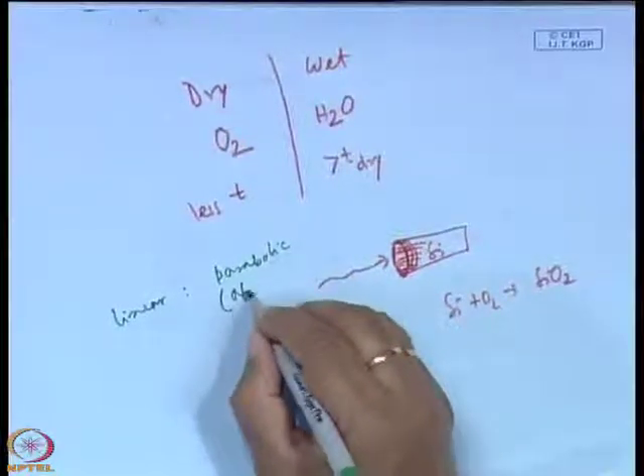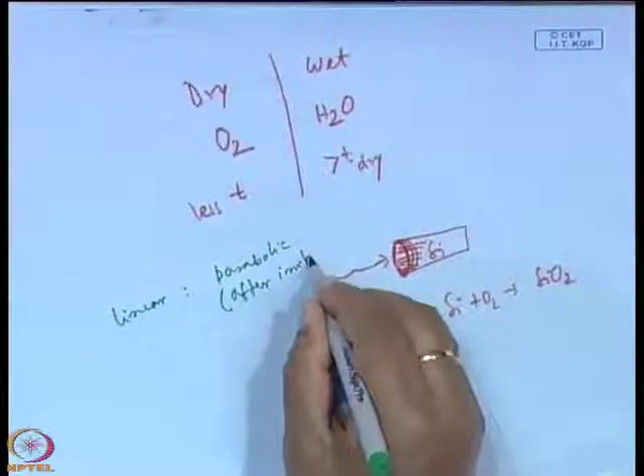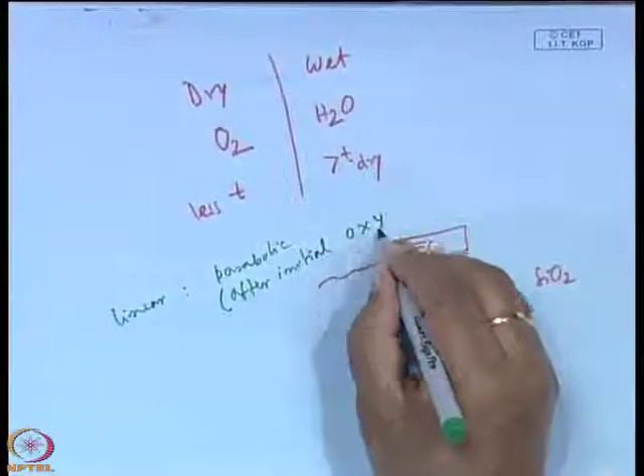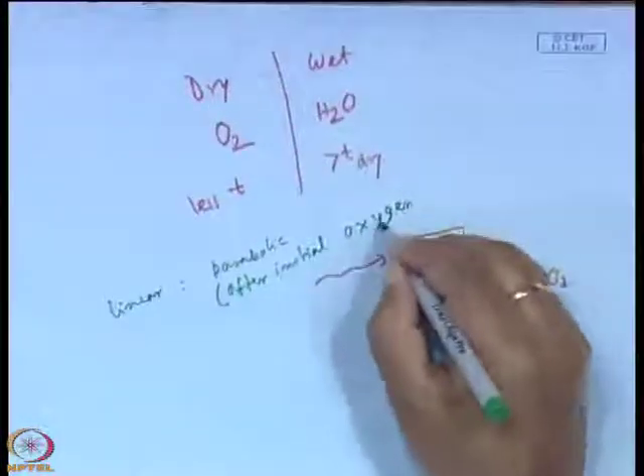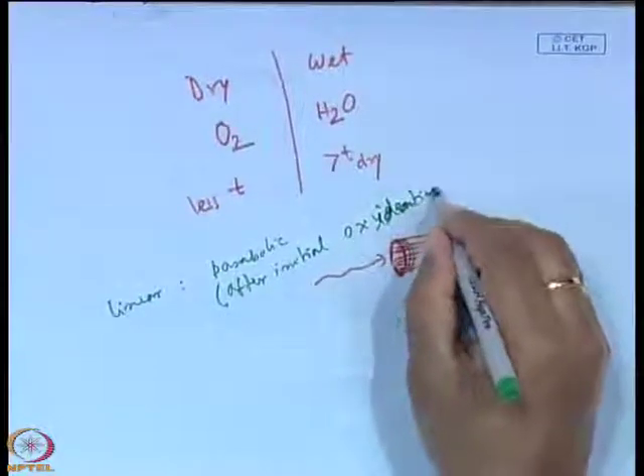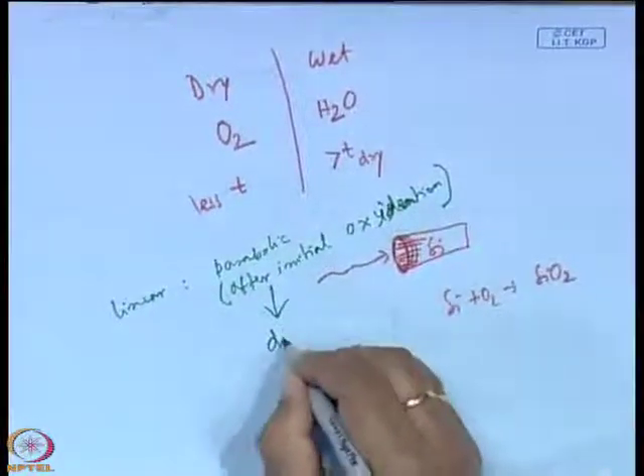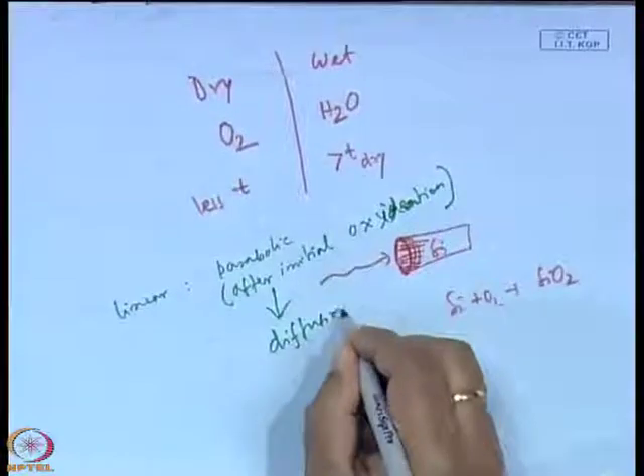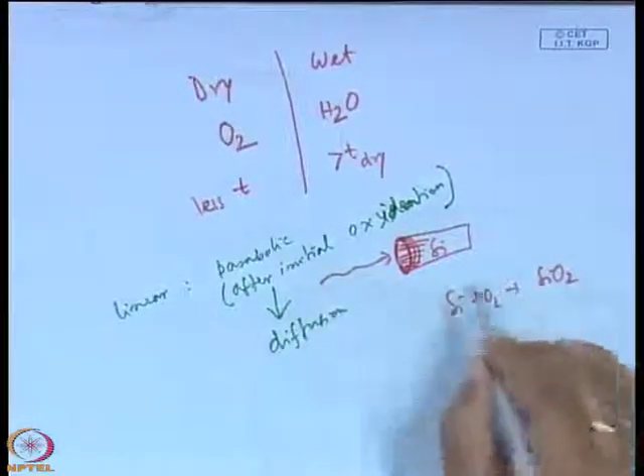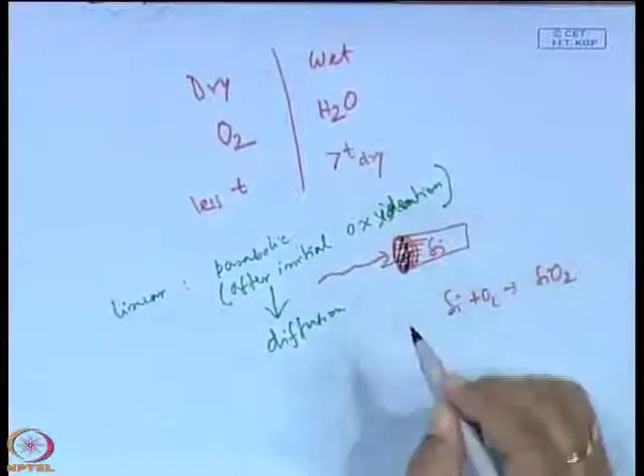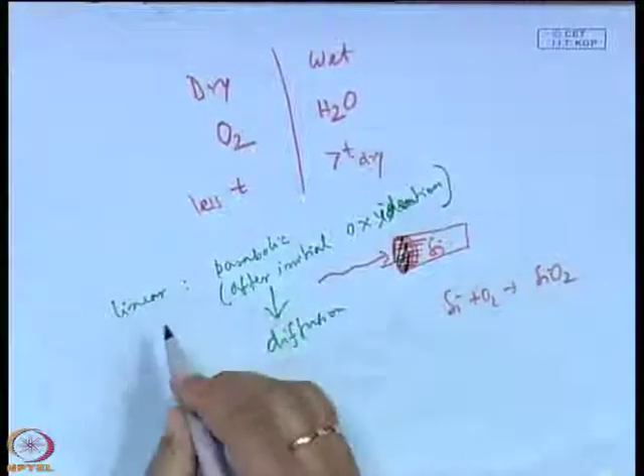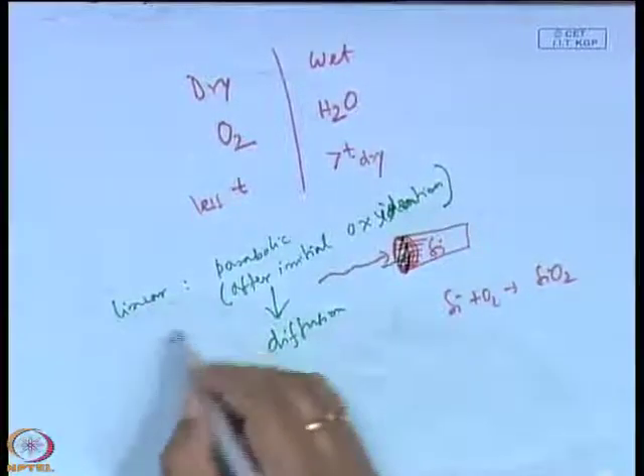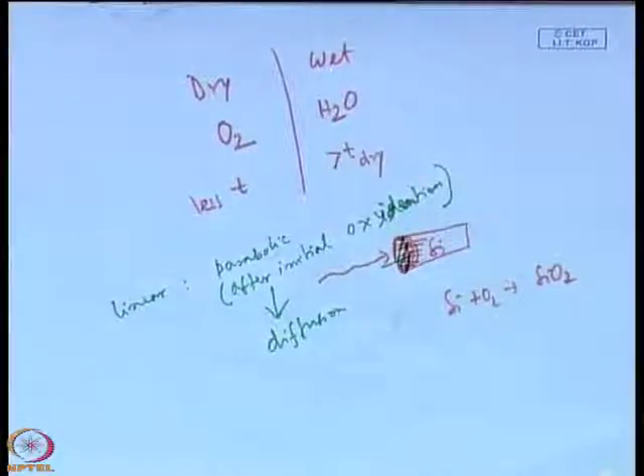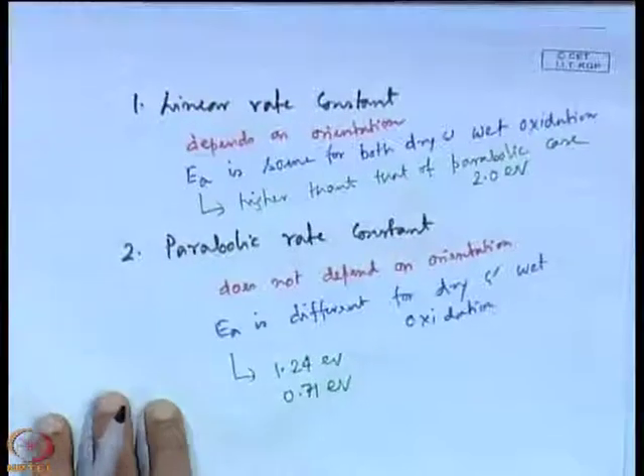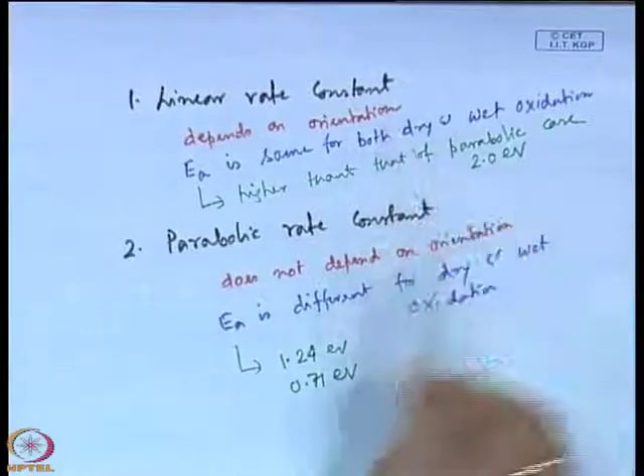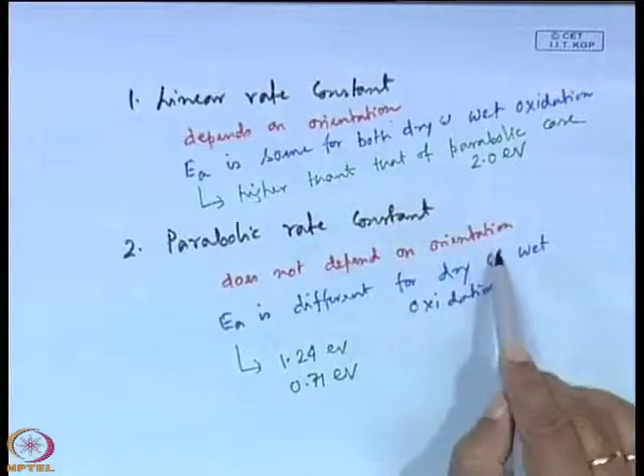This is after the initial oxidation, because diffusion takes place through this initial layer of the oxidation. The linear rate constant, we have seen, depends very much on the orientation of the crystal, as we have discussed, whereas the parabolic rate constant does not depend on orientation.